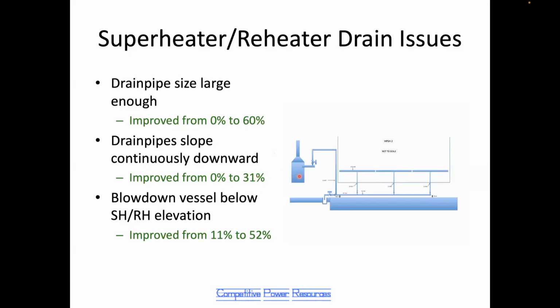This cartoon shows the blowdown tank that the water must move to, elevated above the superheater lower headers. This is unfortunately a very common practice. It's gotten better from 11% to 52% where it's located low enough, but this is still a common problem. A favorite workaround for that is to add a drain valve here so that during startups from zero pressure, the water can flow by gravity into a sump. And then once pressure gets up to about 2 bar, you close this valve, and that's enough pressure now to move the water into the blowdown tank.